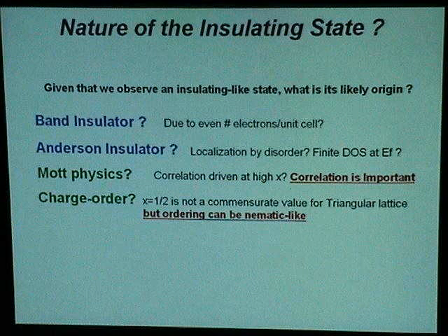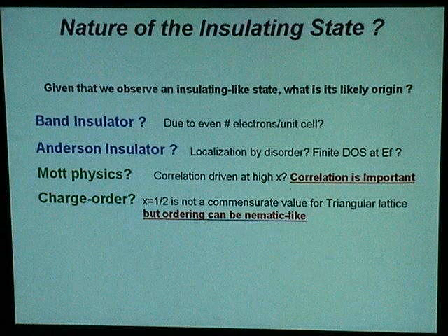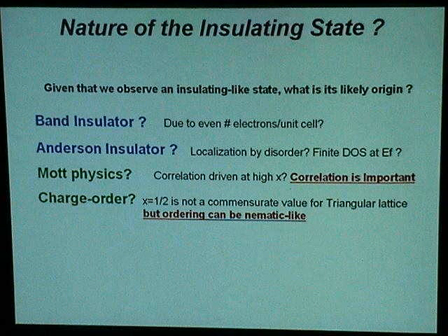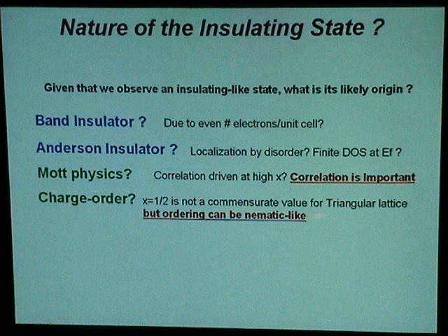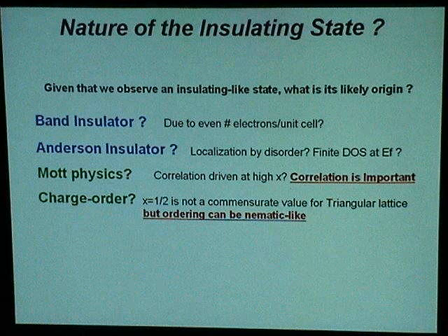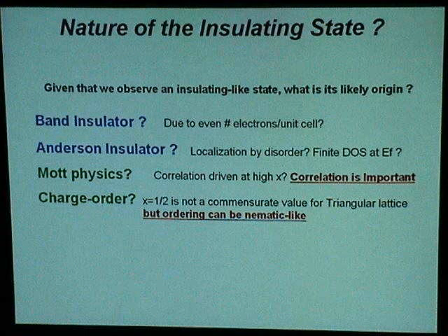But to argue that this is Mott physics, one should realize that this is very high doping compared to, say, copper oxides or other things. This is 50% doping, way overdoped. So charge order, it's 1/2, so it cannot be commensurate. One possibility, consistent with neutron observation, is that this antiferromagnetic stripe order leads to some sort of nematic type charge order, which is possible at 1/2. But commensurate charge order is not possible.